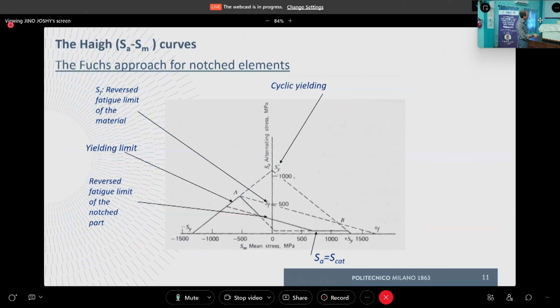Tac. And here the limitation is yielding. Okay, here the Fuchs diagram is larger than the traditional one, and so this is the limit. And we can enter this Haigh diagram the usual way, starting from the basic point with the residual stress and then going up according to the fatigue cycle and the ratio between the amplitude and the mean stress.